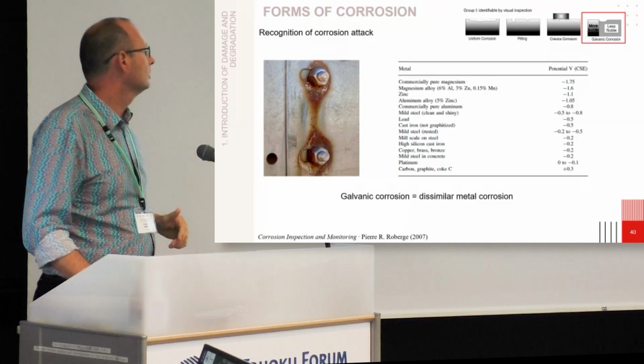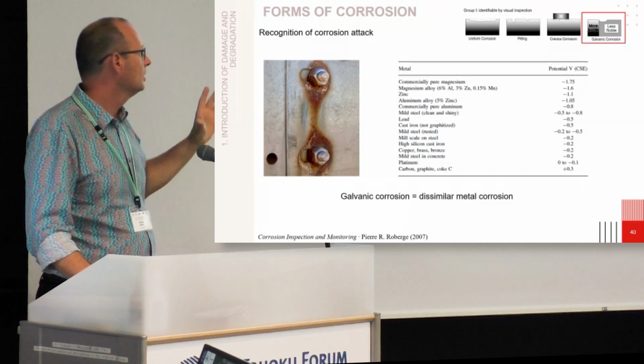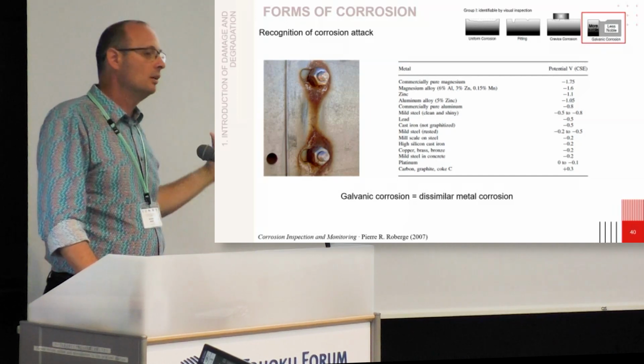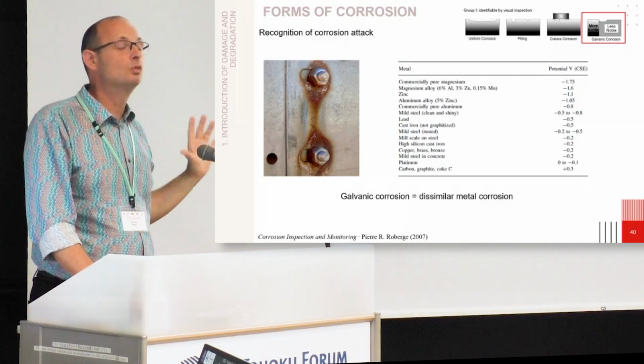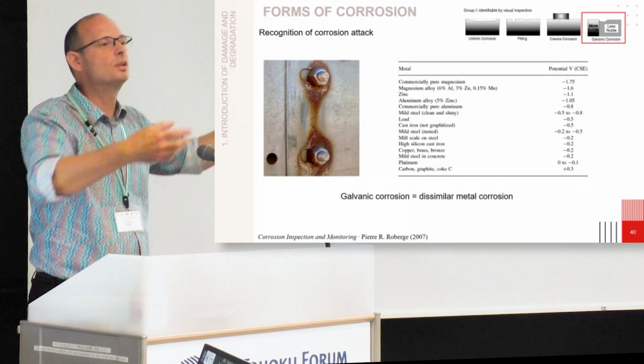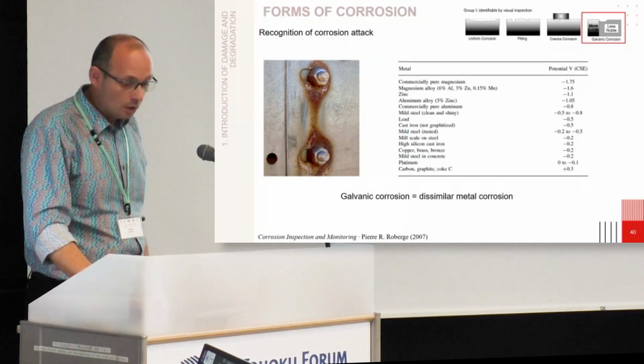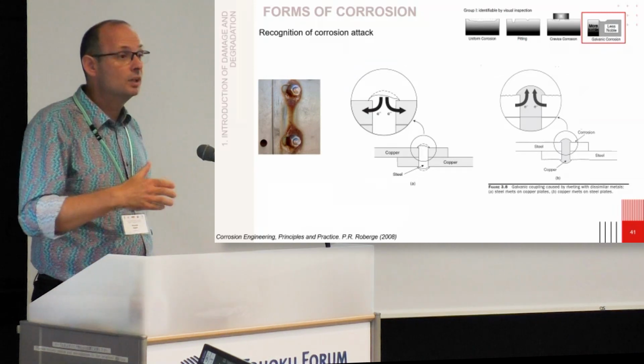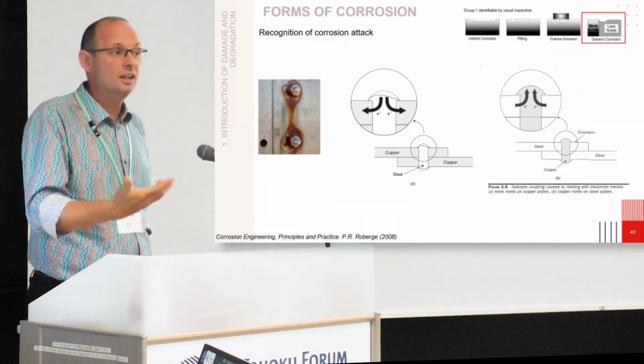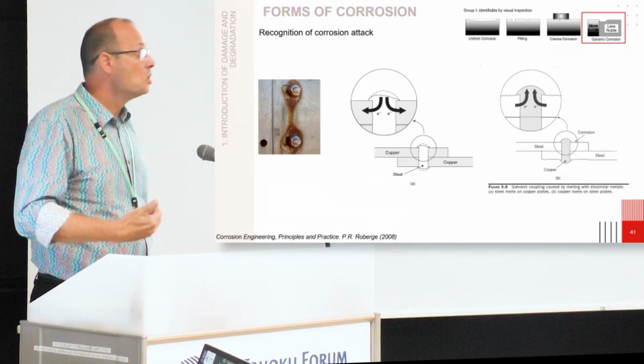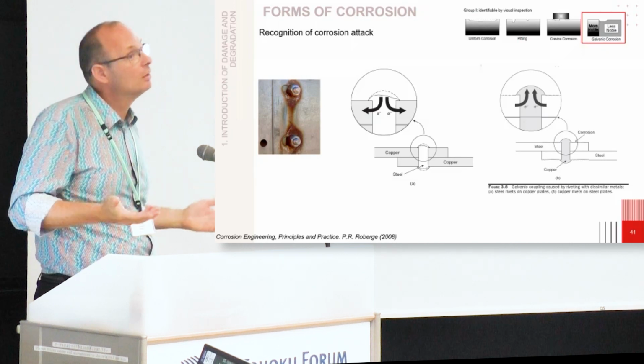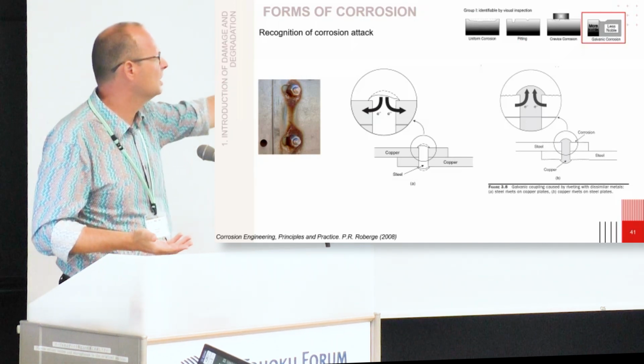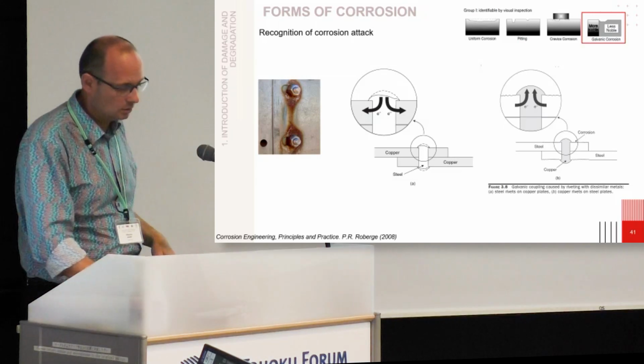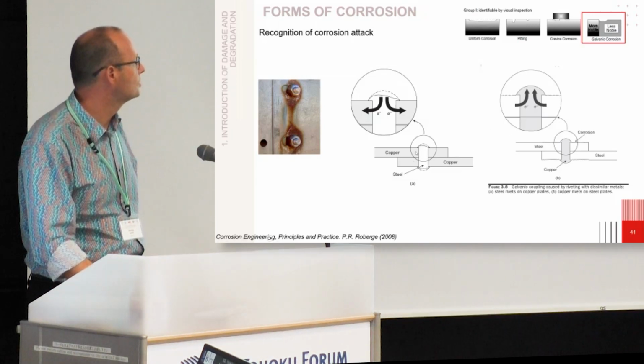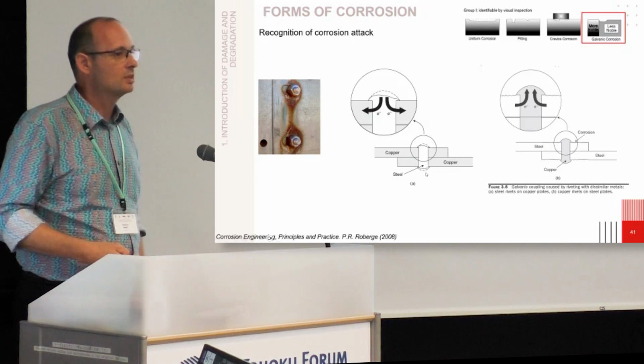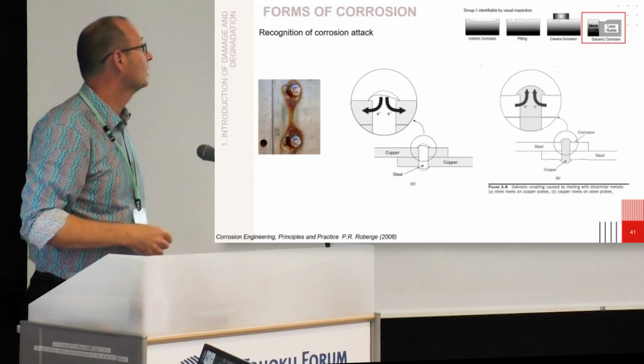This is the one typical corrosion that we can find when designers are not aware about corrosion. It's because they select two materials, because it's easier to make an infrastructure. The problem is the two materials have significantly different corrosion potentials. So that means one will be protected when the other one will dissolve. This is typically the case when you try to make some soldering with copper and steel wire, for example. In this case, the steel wire will dissolve very fast.